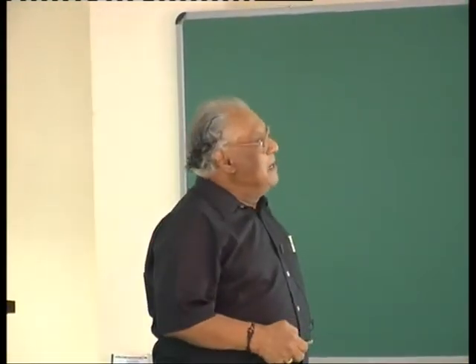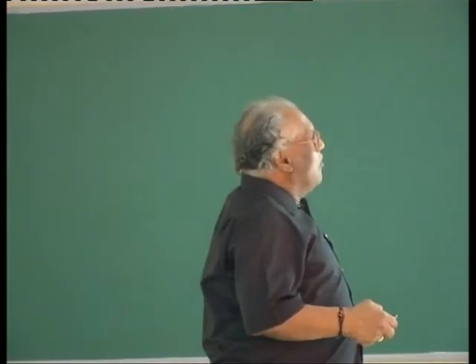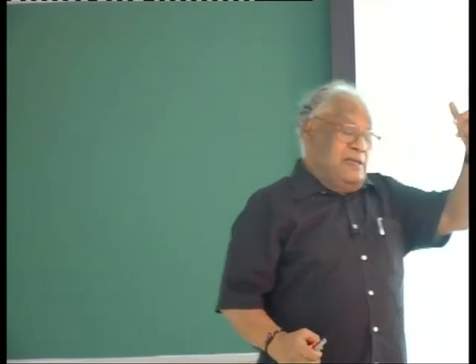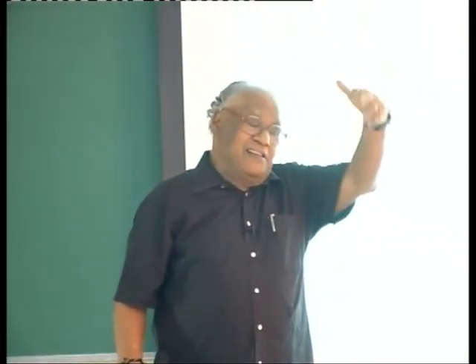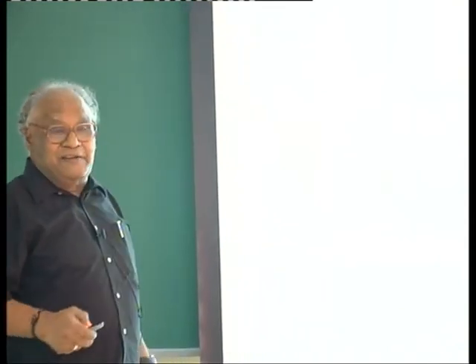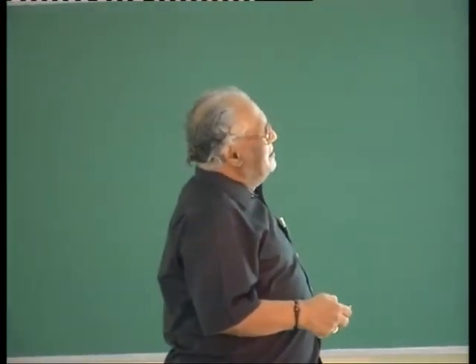So we have now made a general rule. We have made chromites. Again, Sundaresan has done that. Rare earth only with magnetic rare earth ions, like samarium, as Scott did with the iron oxide. He did the iron oxide with samarium, and he said it was ferroelectric in the PRL recently. And we have shown a large number of chromites. We didn't do ferrites because in ferrites the magnetic transition temperature is very high, and we can't do measurements at that temperature. So we did chromites where the transition temperatures are low.